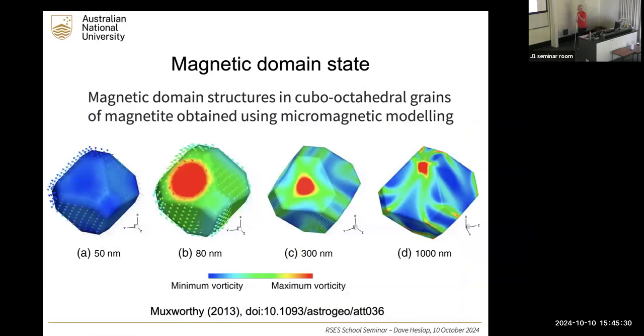Similarly, with grain size changes, this is magnetite. This is work done by Adrian Muxworthy at Imperial College London. It's a numerical model of what the structures of magnetic particles look like as you change the size. So these are magnetite particles, 50 nanometers through to 1,000 nanometers. They all have the same shape. The only thing that's changing is their size. And the way that they're modeled is to split the crystal into a collection of elementary dipoles, basically just splitting it up into a load of tiny magnets. And then you work out what the lowest energy state for that particle is using this finite element approach.